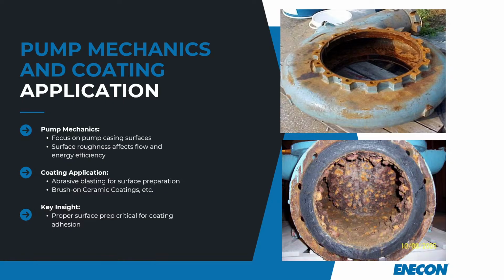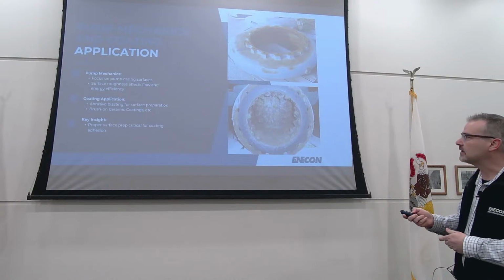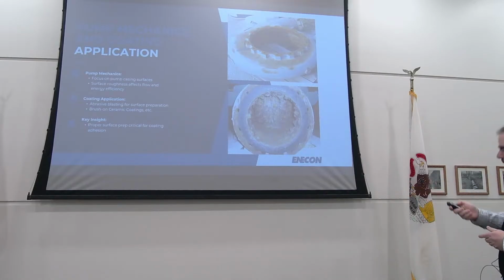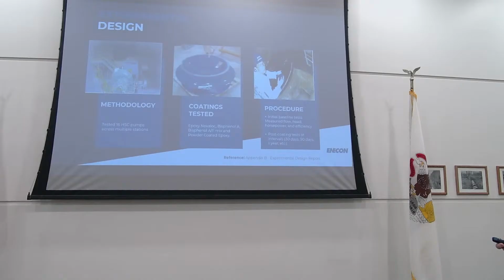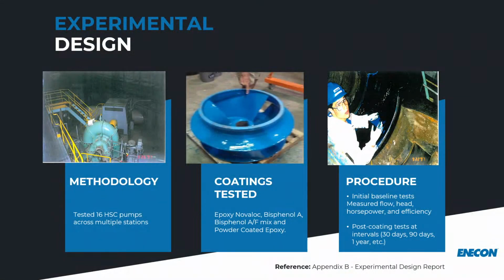Here's the coating application. So when you're doing that, you do have to sandblast, right? Proper preparation prevents poor performance. So they would always follow the manufacturer specification. Typical application is going to be 2 coats, maybe 6 to 8 mils thick per coat. But the key is, of course, you want to get that proper prep, because if you're just going to sand it down, you might have some issues on it, especially if you're doing the entire interior of a pump or a volute casing. So here we go, the methodology: 16 horizontal split case pumps across multiple stations.